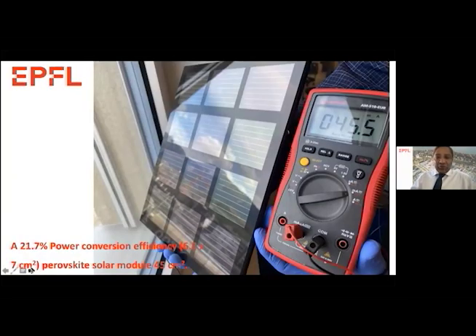So instead of going for large-scale production, what we did is take our mini modules, that's a 7x7, and integrate them into A4-size mini modules. And the current, you can see, is 45 milliamps already at room light conditions. The power conversion efficiency at that time was 21.7%. Today in the lab, which we have sent to Newport for certification, we got 23% on the mini module size. This is quite a remarkable achievement with respect to power conversion efficiency, close to silicon solar cells.